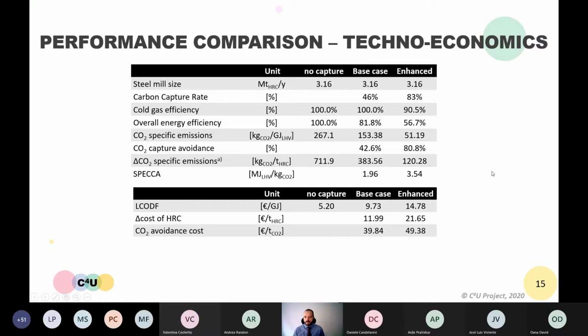indicators. In terms of economics, we can see that the cost of the decarbonized fuel from the starting cost of 5.2 euro per gigajoule will rise up to 9.7 and 14.8, depending on the level of CO2 purification we can achieve. And this also translates in terms of CO2 avoidance, which goes from 40 to 50 euro per ton. These are numbers based on the assumptions that we have used and with the BFG composition that is being considered.